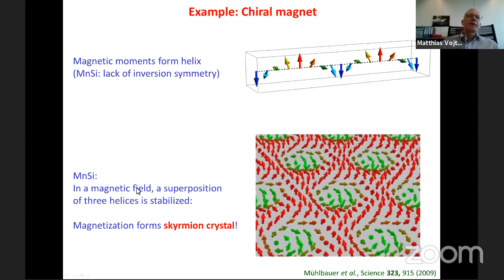Namely, in manganese silicide, it has been shown that in a particular regime of magnetic field and temperature, a state which is a superposition of 3 of those helices propagating in 3 different directions is stabilized. And most interestingly, this is a picture of this particular state here. This state, which is a superposition of 3 helices, can be understood as a skyrmion crystal, meaning a lattice of topological skyrmion defects in a homogeneous magnet. So this is a state which in a certain real space sense has topological properties.